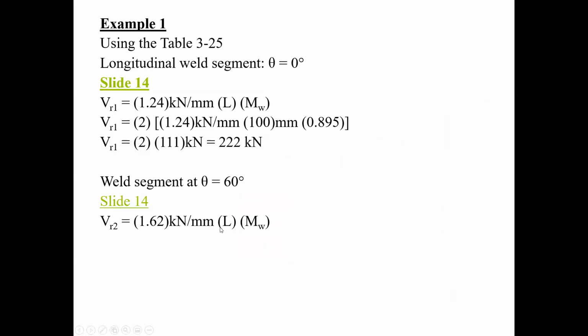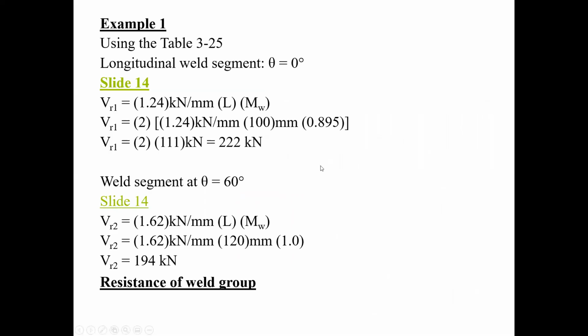So I have 1.62 times L, and this stays the same. Therefore, I multiply these two together times 120, and end up with 194. And of course, the sum of all the weld segments gives me the resistance of the weld group, exactly the same as what we got before.